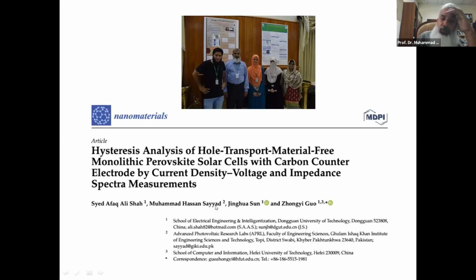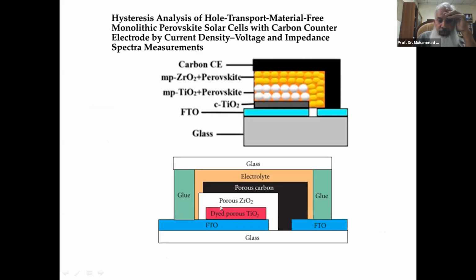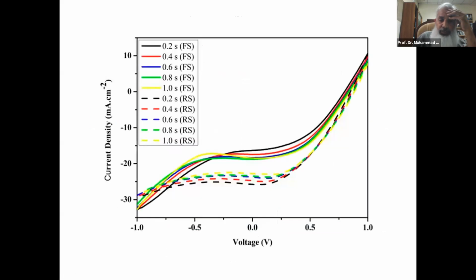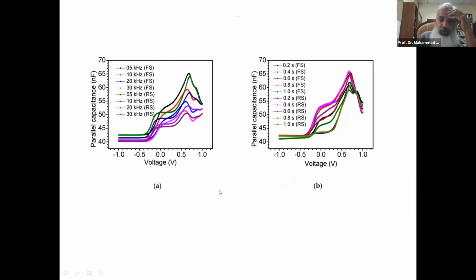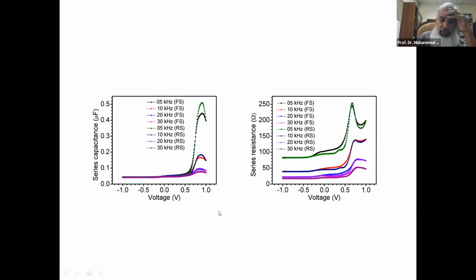So the photovoltaic parameters depend largely on the sweep direction and sweep delay. And there is a lot of hysteresis found in that. You can see here that in the forward sweep, the performance is very low as compared to the reverse sweep. That was the hysteresis we studied in the impedance spectra of this device.